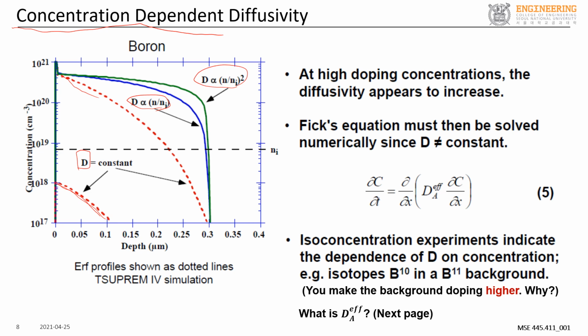When the concentration is low, this doesn't play much role, right? Because when the doping concentration is low, N will be similar to Ni anyway. So even if you use these models, the D will still not change. With this different model for D, they stay the same. But when you have a high doping concentration, N will be actually larger than Ni, or even much larger than Ni.